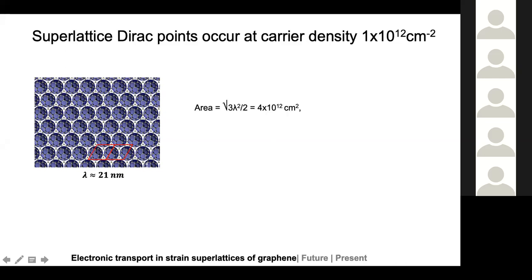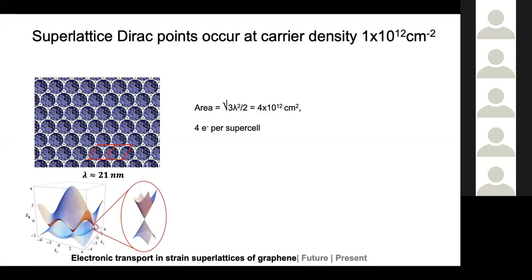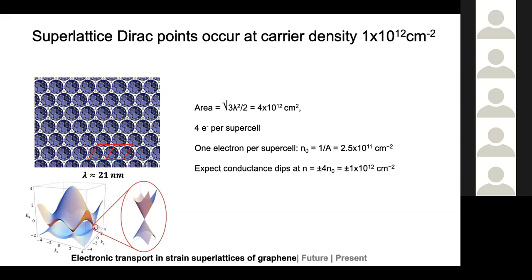Using that, you can estimate the area of this rhombus as 4 into 10 to the power minus 12 centimeters squared. And you need to include 4 electrons per supercell because there is a spin degeneracy of 2. And in graphene, since the K and the K prime points are not equivalent to each other, and there are 2 atoms present in your unit cell, you'll have an additional valley degeneracy of 2 electrons. So in total, there will be 4 electrons per supercell. So you can estimate if you had 1 electron per supercell, what your carrier density would be. And then if you multiply that by 4, you get the desired superlattice carrier density, the carrier density per supercell. And the conductance dips happen when the supercell is completely filled up.